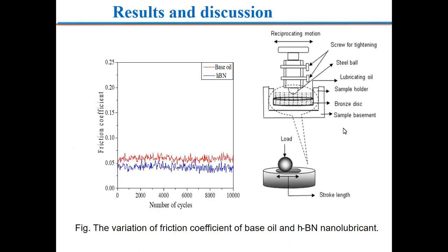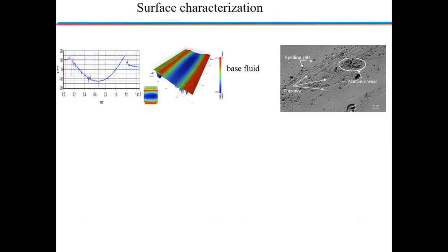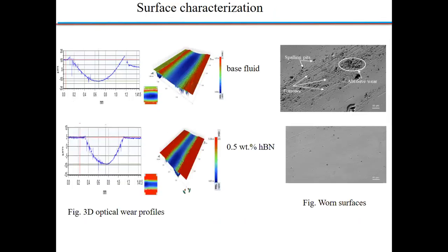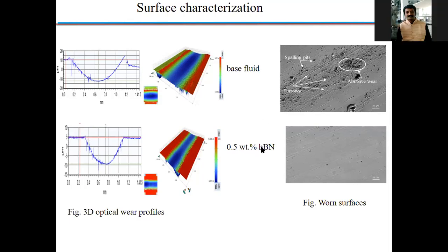It is because of hexagonal boron nitride particle based nano lubricant. You can also do the surface characterization using a 3D profilometer. This is the base fluid. In the image of the base fluid, you can see the reduction in width of wear. A significant reduction in width is there in the case of HBN based nano lubricant. This is for base fluid, and 0.5% weight of HBN results in a significant reduction in width of the wear track. So this is the advantage of HBN nanoparticles.